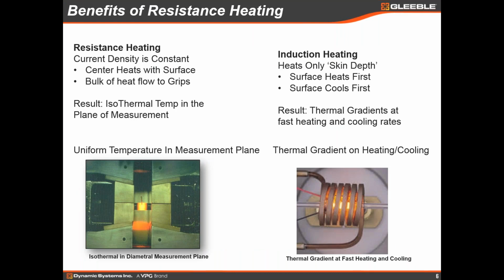So I'd like to take just a moment to talk about the benefits of the Gleeble when you're doing dilatometry. The Gleeble is a bit unique in the world of scientific simulation equipment in that we use direct resistance heating to heat our sample. So what this means, and I'll compare and contrast this a little bit to induction heating, although the same points will apply to furnace heating. In a Gleeble, we clamp a metallic sample between two grips, usually copper, maybe stainless steel, that are mounted in water-cooled jaws.